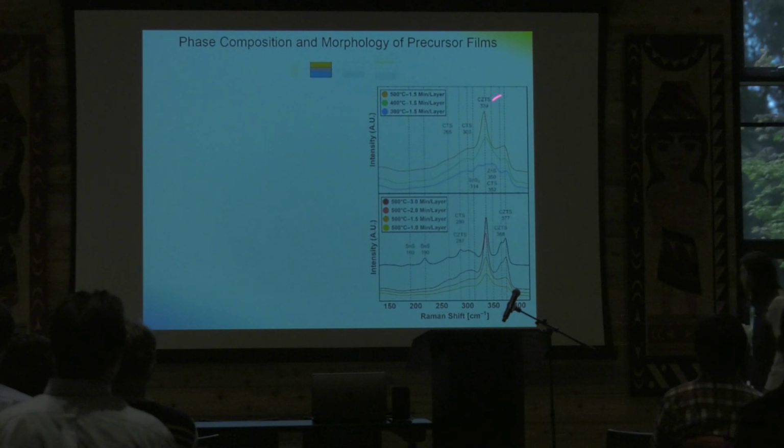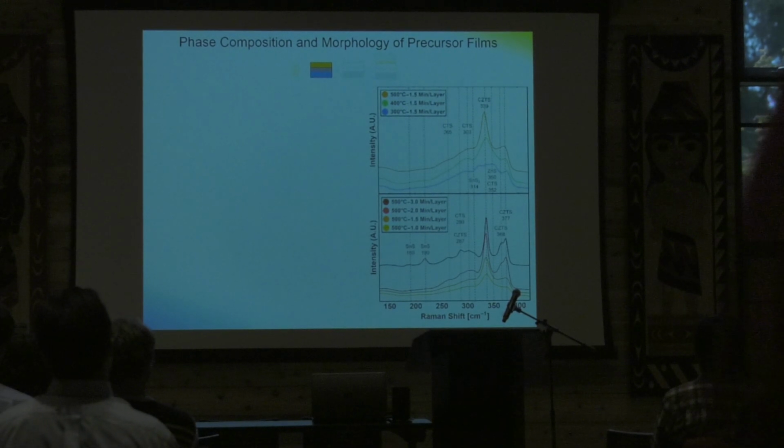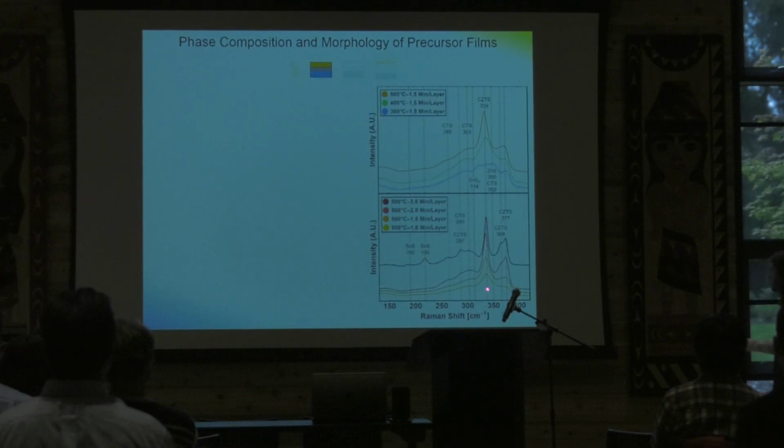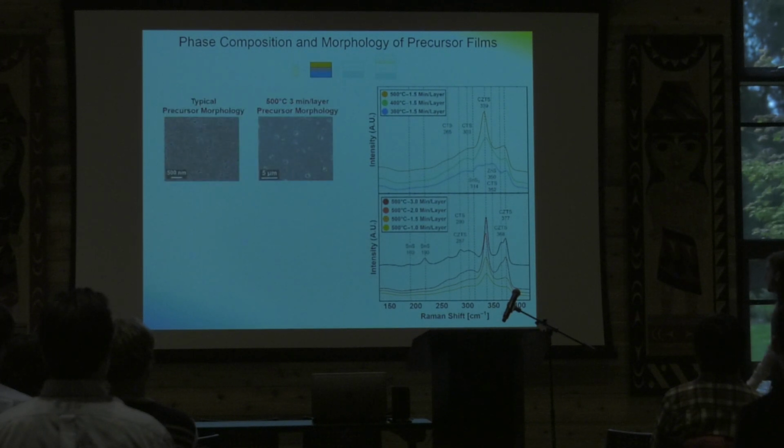And if we go through and label these chemical phases, what you can see is there's a lot going on here because there are a lot of different metal sulfide phases that will form, but generally for the lower temperature anneals, you're forming binary and ternary metal sulfides. And then for higher anneal temperatures with increasing time, you see more and more of these CZTS phases.